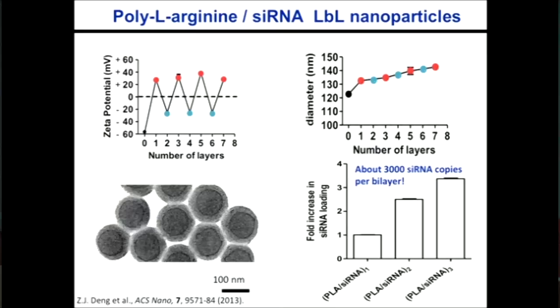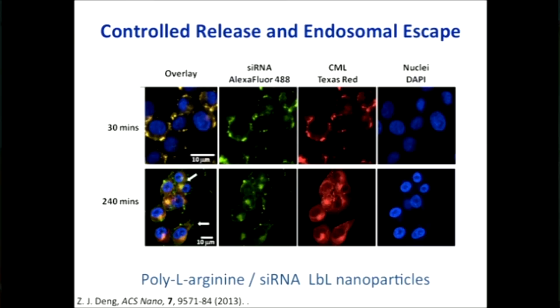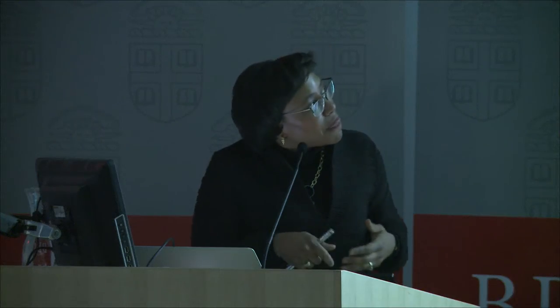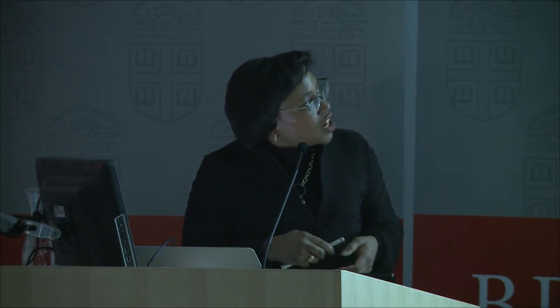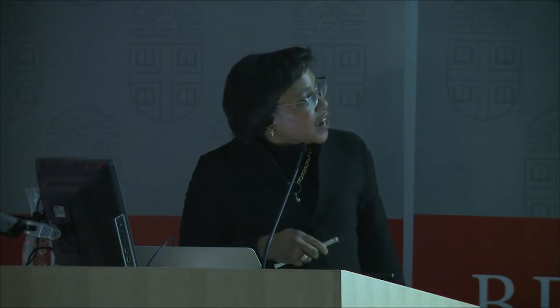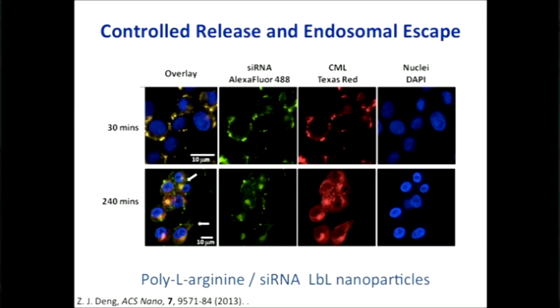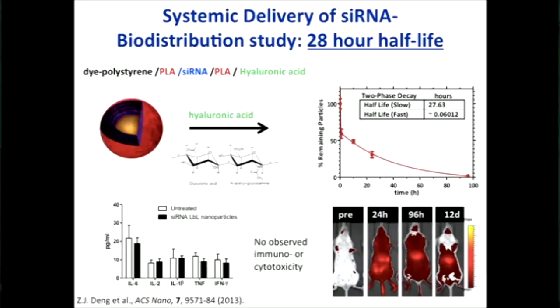Here you can actually see a close-up of these layer-by-layer systems again, for those of you who are interested. When we adsorb siRNA into the layers, we get about 3,000 copies or 3,000 siRNA molecules on average per nanoparticle. So we have a nice loading of these systems with just one bilayer. And we see that we can get very controlled release of the siRNA in the cytoplasm of cells in in vitro experiments. So let's move right on to examining these systems in the body.